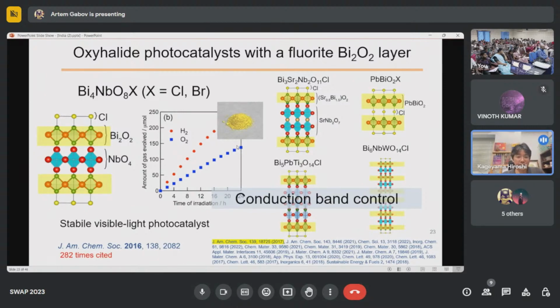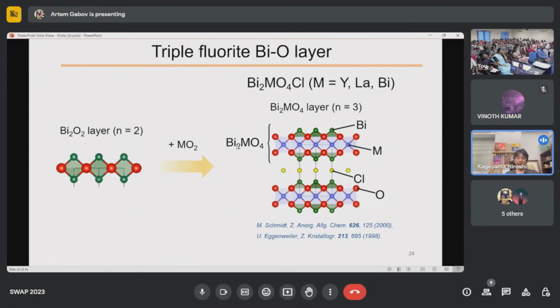After this discovery, we found a series of similar compounds, which is summarized in these papers. By changing the composition and the combination of the structures, we are able to control the conduction band maximums. Then the question is, what happens when we increase the number of layers in this double bismuth 2O2 layer? Actually, there are only a few examples of the triple layer, I mean the Bi2MO4 layer. This was reported about 20 years ago.